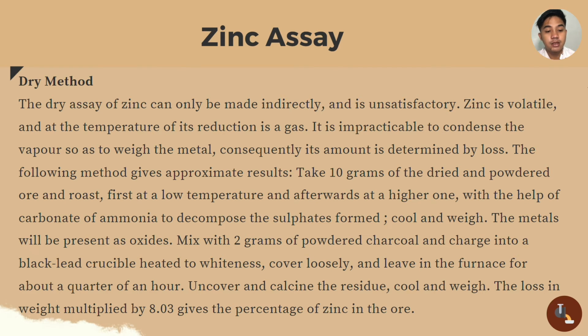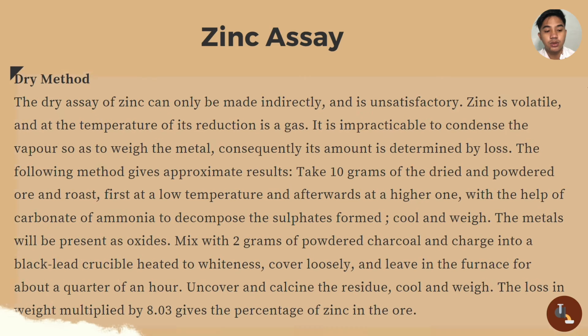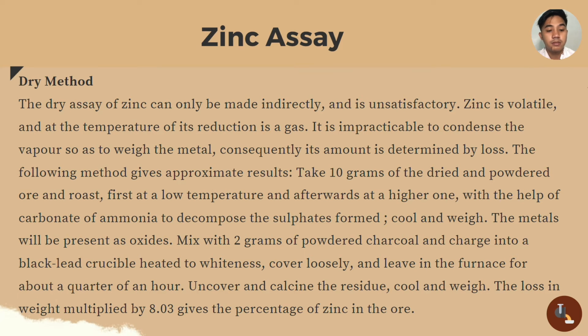The materials will be present as oxides. Mix with 2 grams of powdered charcoal and charge into a black lead crucible heated to whiteness, cover loosely, and leave in the furnace for about a quarter of an hour. Uncover and calcine the residue, cool and weigh. The loss in weight multiplied by 8.03 gives the percentage of zinc in the ore.